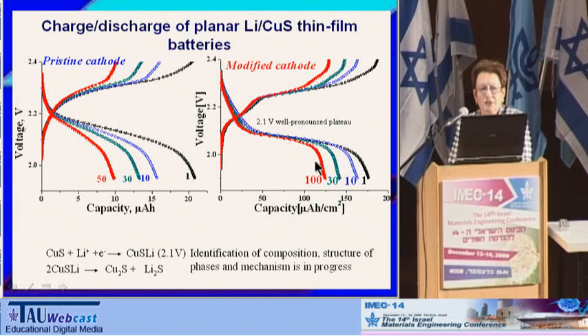The next slide shows some results of the electrochemical testing of the planar lithium copper sulfide thin film batteries. A pronounced plateau at about 2.1 volt is detected in the discharge curves, and here you can see the number of the cycles the cell was tested. The pronounced plateau was detected in the cells which comprise modified cathode. However, the cells with a pristine cathode have some slope here, and the charge discharge curves are steeper.